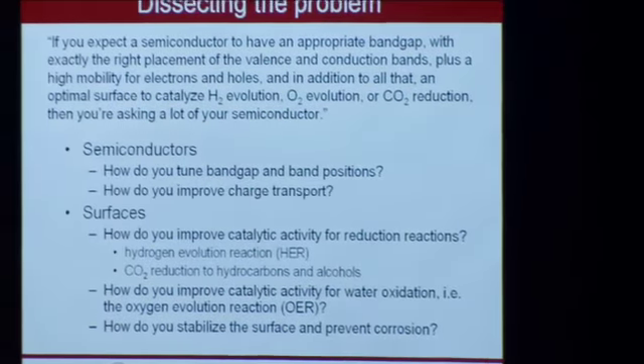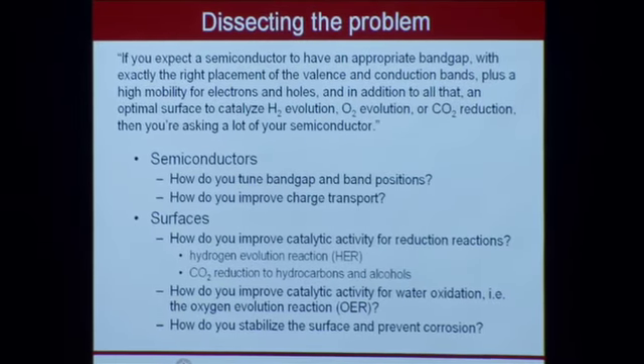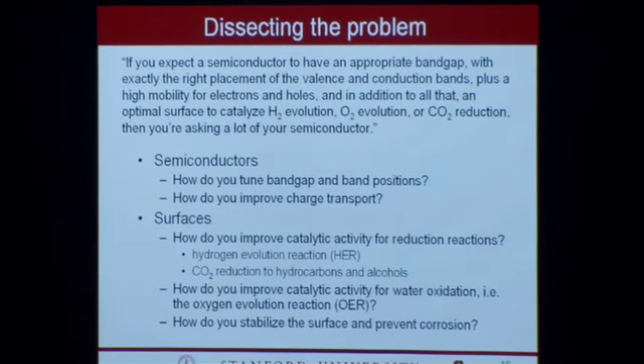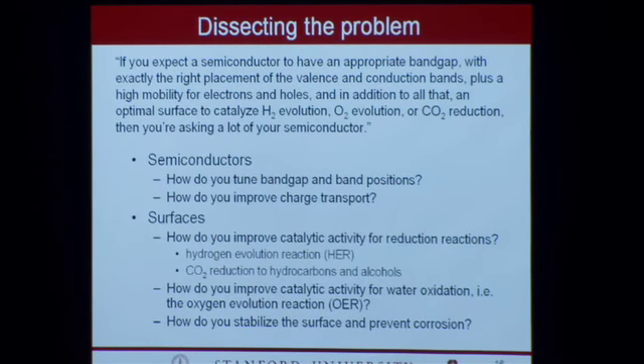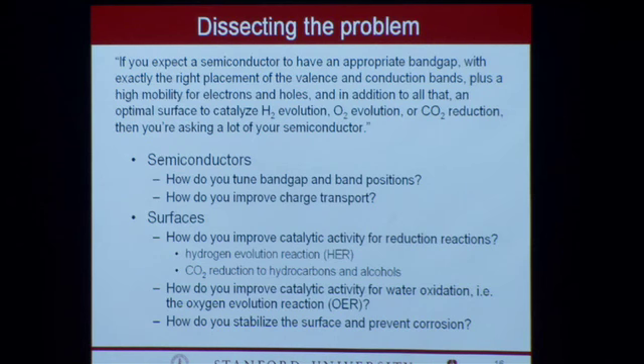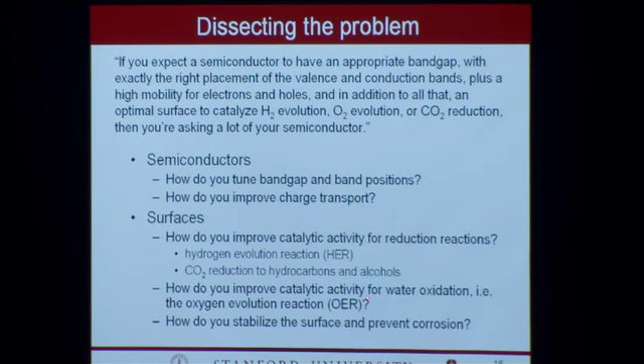You need to evolve hydrogen effectively, reduce CO2 effectively. And both of these reduction reactions, guess what they need? They need electrons and holes. So the question then becomes, where do you get your electrons and holes from? You don't want to oxidize methanol in order to produce methanol on the other side. That makes no sense. We'd like to oxidize water because it's free and abundant. So we want to improve catalytic activity for water oxidation, which is otherwise known as the oxygen evolution reaction. And then, of course, we want to stabilize the surface and prevent corrosion of our semiconductor.